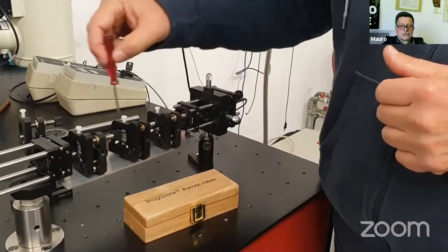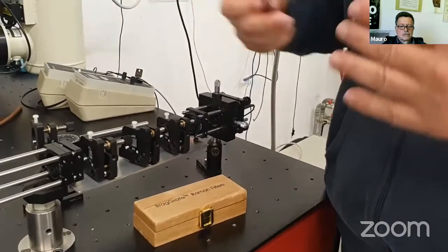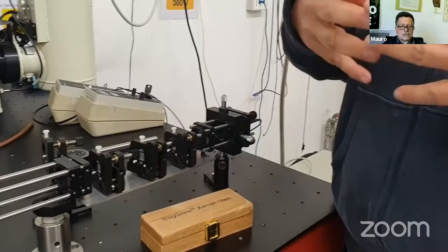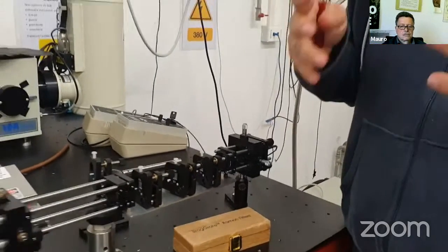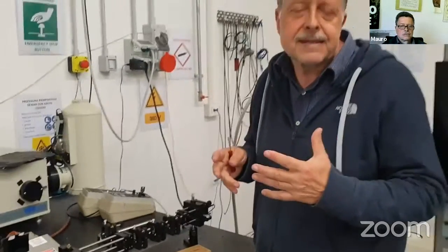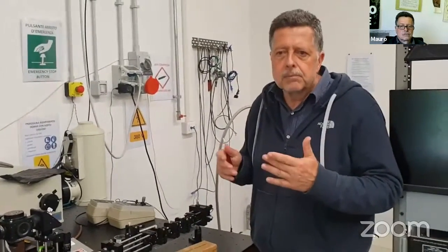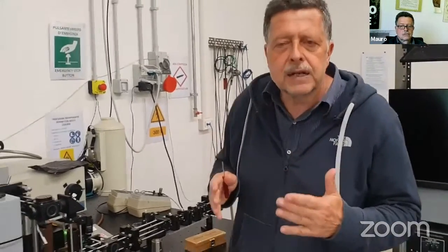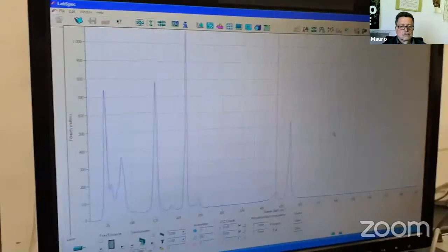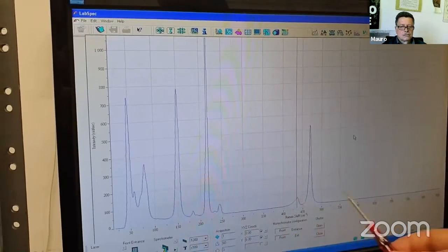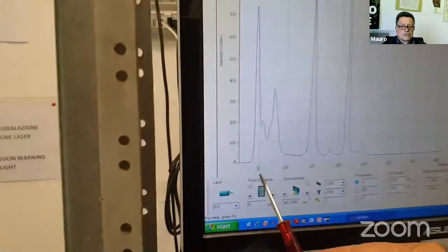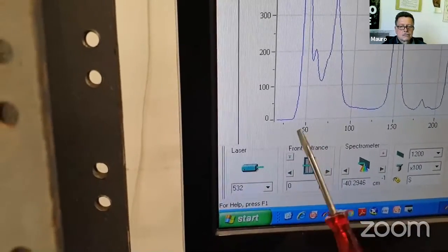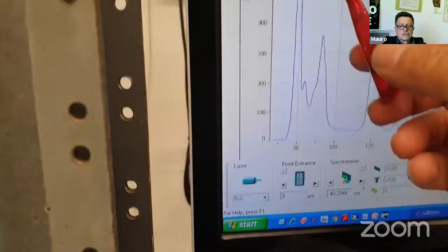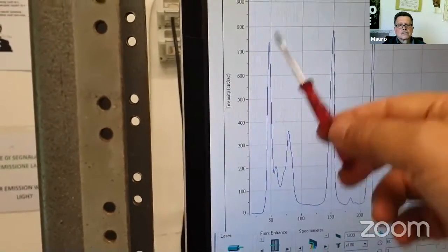In this experiment, we have 3 filter holders, because we can put filters in cascade to improve the rejection of the laser light and to be able to measure the Raman lines very, very near to the laser line. You can see this here. This is, for example, the Raman spectrum of sulfur, and you have lines down to 50 centimeters to the -1. That is, the laser is very near here. To measure these lines, you need very good optical quality filters. And this can be done with this system.